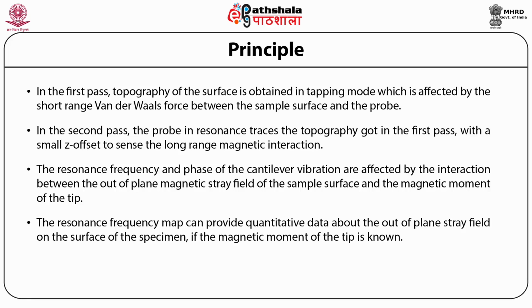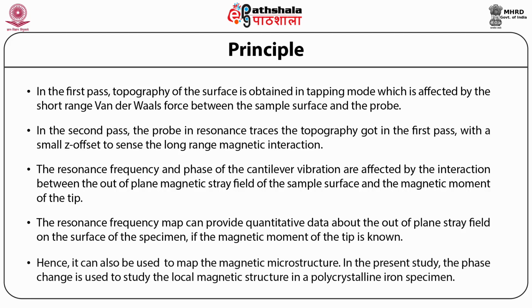The phase map can provide qualitative data about the changes in the out-of-plane stray field along the surface of the specimen. Hence, it can also be used to map the magnetic microstructure. In the present study, the phase change is used to study the local magnetic structure in a polycrystalline iron specimen.